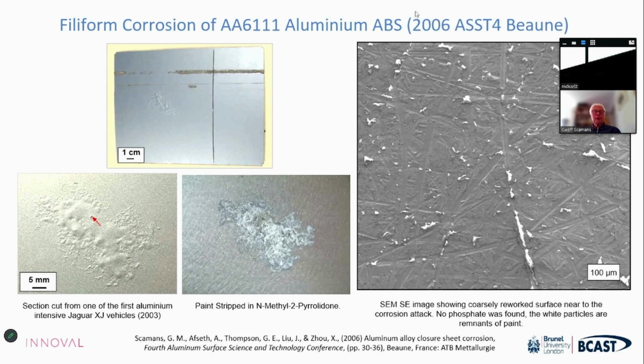So I was sent a car door, which is from one of these lovely cars that have been exposed to the environment in Hull, not particularly best or particularly worst environment on the planet. When we were able to look at that surface, we could see where the paint had been damaged by a stone chip, where the red arrow is. We could see the aluminium hydroxide corrosion product when we stripped the paint off in a nasty organic solvent. And you could see that the surface of the aluminium sheet was not the rolled surface that we provided to Jaguar Land Rover to make the cars, but it was something that they'd added before they actually did the painting, which was a rectification process involving grinding the surface.